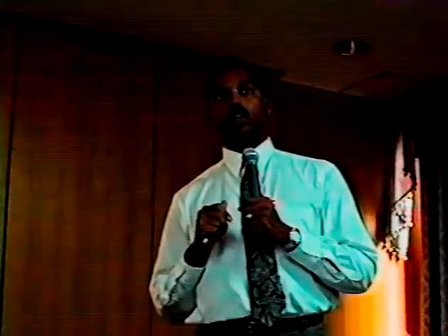In the passivated form, and I should have mentioned that immediately following synthesis we passivate the samples, so there is the presence of ammonia at the surface. We do a reduction, and the results that I showed you, the nitrogen to moly ratios, are those of the reduced material. So we've removed all of the adsorbed ammonia and anything else, free nitrogen, if you will, that's on the surface of the material. So those, I think, are more characteristic of what the material is and not what's on the surface of the material. I think maybe we can close our discussion here.